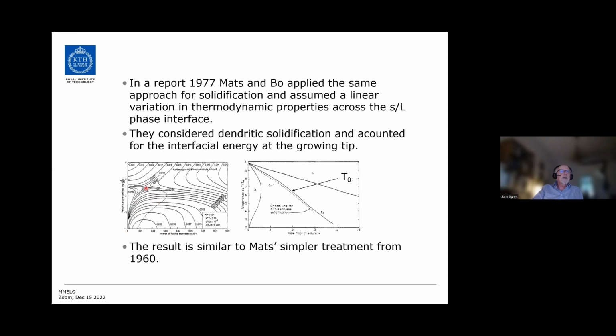And again, there is a critical point. So when the supersaturation becomes bigger than that, the reaction turns diffusionless and goes very fast. And that information, which is for one temperature, is here transferred to the binary phase diagram. And the solid line here is a T0 line, and the dashed line here is the critical points. So when you cool below that dashed line, there will be a spontaneous change to diffusionless solidification.